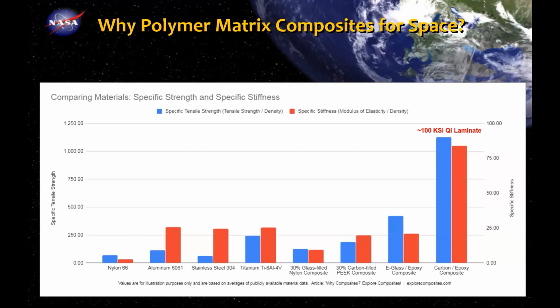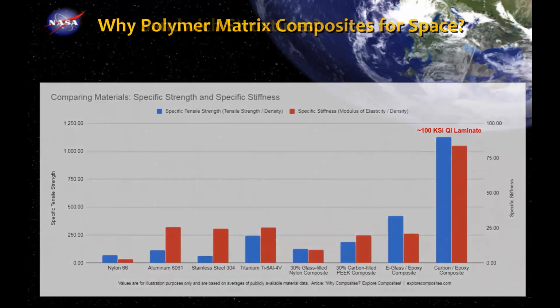But when you think of strength, we can't design to this kind of optimal value. They are still brittle materials. And so when we start to damage the structures, we put defects in that could really be in the structure from impacts or otherwise. We have to knock that number down significantly, by at least half. And you can see then it doesn't become as competitive as it looks on this chart. However, for things like bending stiffness, you still have that benefit, even with damage.